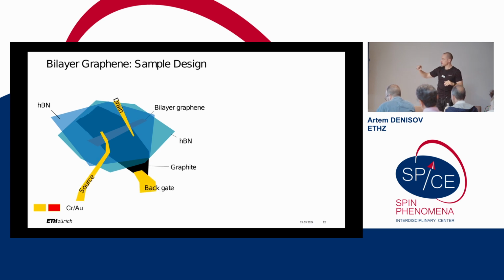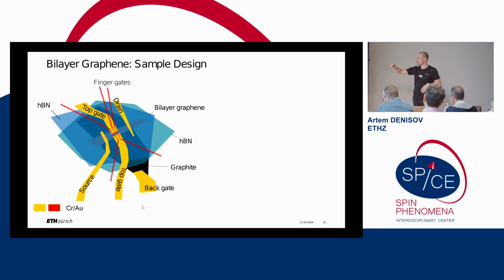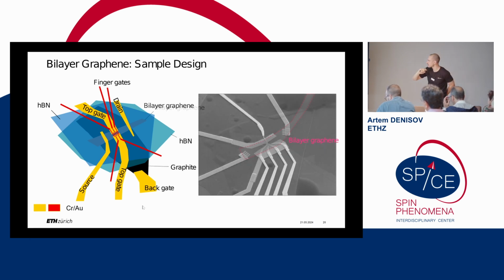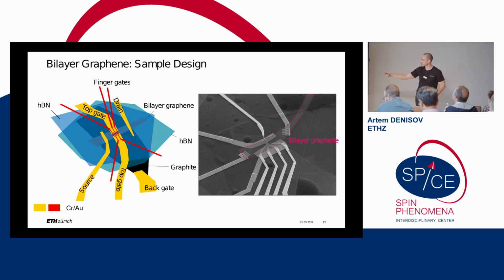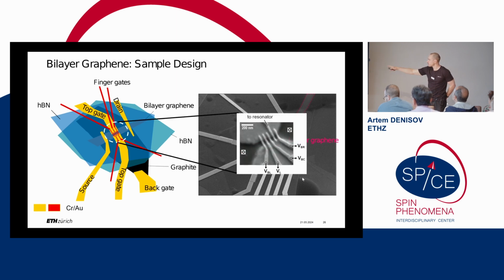In the next step, we put an ohmic contact to the graphene, which we do by the standard 1D contact, by just etching and putting metal to it, also contacting the backgate. And then we put the first layer of metallic gates, which are called the top gate, to form a 1D channel, where then we will form quantum dots using the next layer of metallic gates, which are called the finger gates, these narrow metallic gates. So the resulting device looks something like this. This is a SEM image. Here you can see, although it is very hard to see the flakes, graphene, hBN, backgate, and 2 layers of overlapping metallic gates on top. And of course, if you zoom in, this is kind of the heart of the device, the channel where quantum dots are going to live. In principle, this geometry is very similar to devices in silicon, germanium, or other semiconductor quantum dot devices.